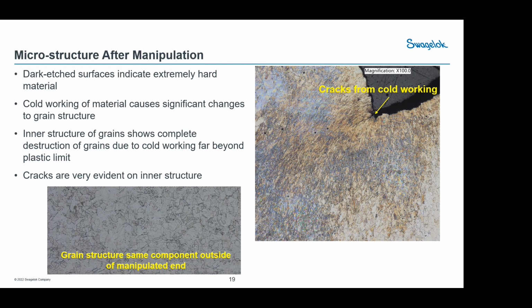Remember earlier I said grain is very important in a high quality steel, so the hydrogen cannot permeate through it. What we found on one of these manipulated ones, this one happens to be the ID is up above, is that a few different things happened. You'll notice these dark gray areas on the upper right picture. Those dark gray areas are actually burn marks from when the etching is done to see the grains. That happens when there's significant cold working taking place, or significant cold stresses being put into the material.